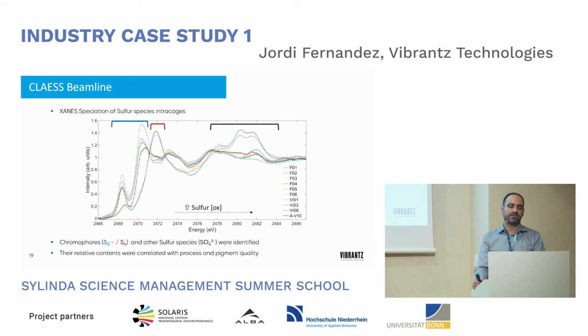speciation of the sulfur species, because you have to bear in mind that the molecular weight of the ultramarines is around 1,000, and the sulfur species is 32 times 3, so it's 96. So it was less than 10% of the weight in the structure. In this case, these studies allowed us to do some fine tuning in some of our synthesis procedures in the lab and also in the factories, to produce pigments with higher tinting strength than the ones that we were producing in the past.